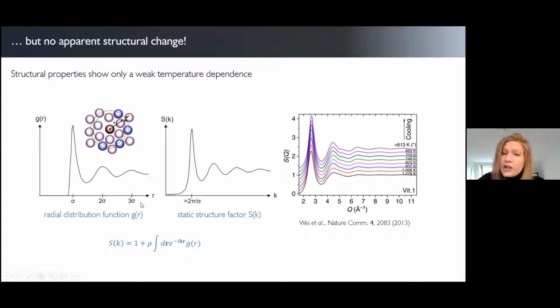If you take the Fourier transform of this function, you get essentially what is called the static structure factor, S(k), where k is a wave vector. And this is a function that people usually measure experimentally in scattering experiments. But it contains essentially the same information as a radial distribution function. So it's a two-particle correlation function.